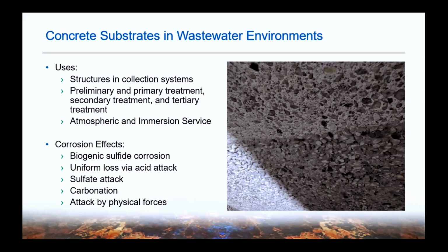Concrete in these environments is going to be exposed to atmospheric corrosion, but then also many of those corrosive forces that we just mentioned in immersion service within these structures. So, as we've alluded to, concrete can see various corrosion effects, including biogenic sulfide corrosion, where that Portland cement is attacked. And like I mentioned, if left undetected, that can be very, very catastrophic in some cases. We also see acid attack by sulfates. I mentioned carbonation as well as the physical forces.